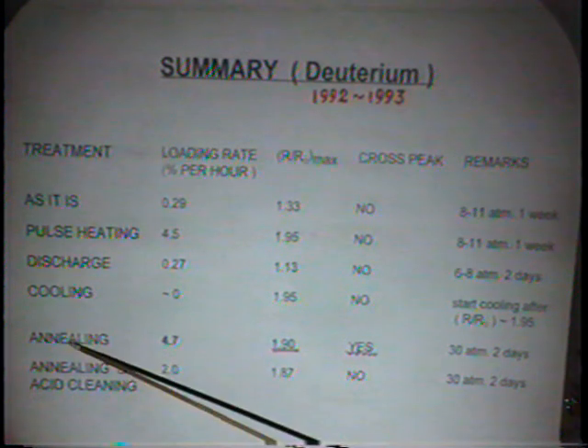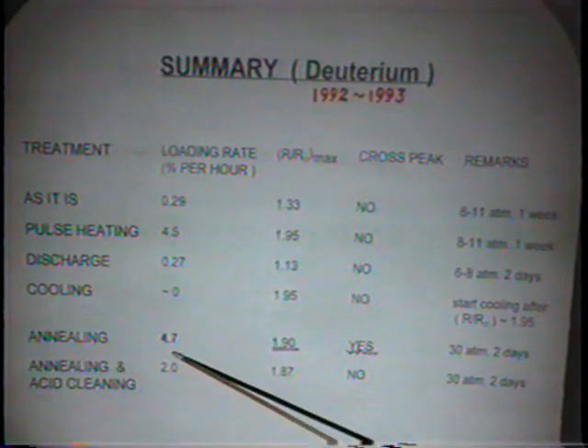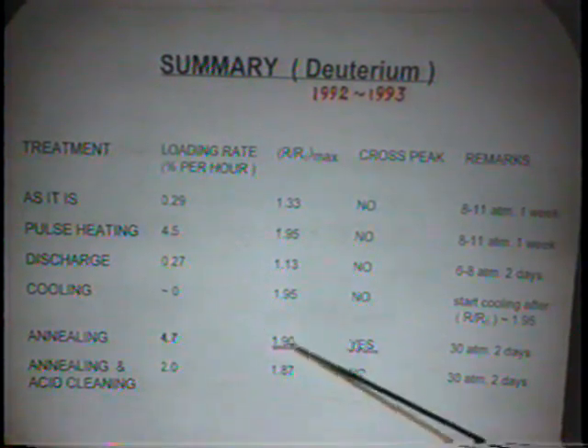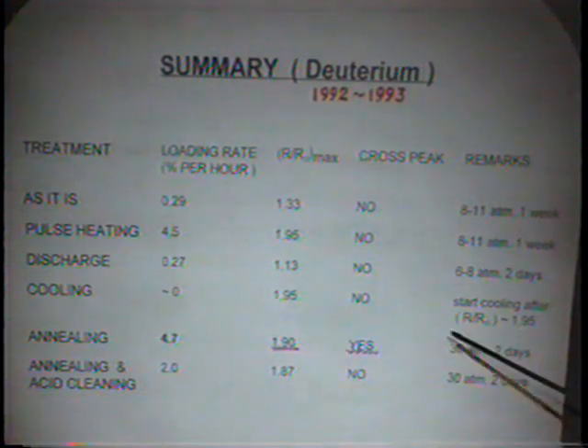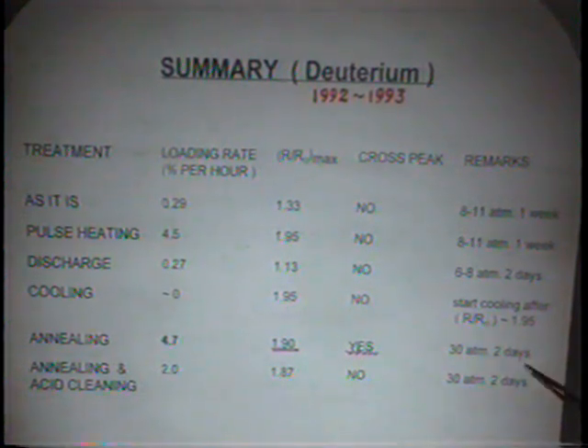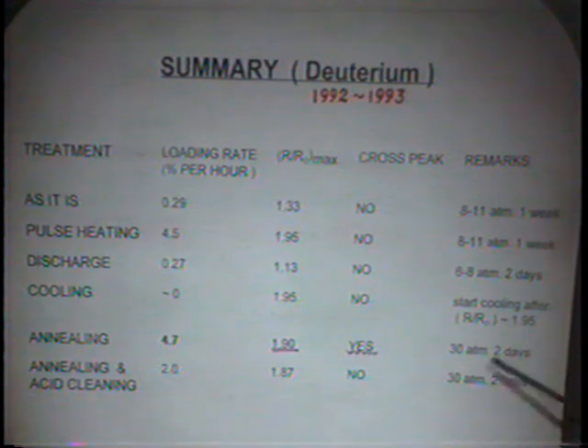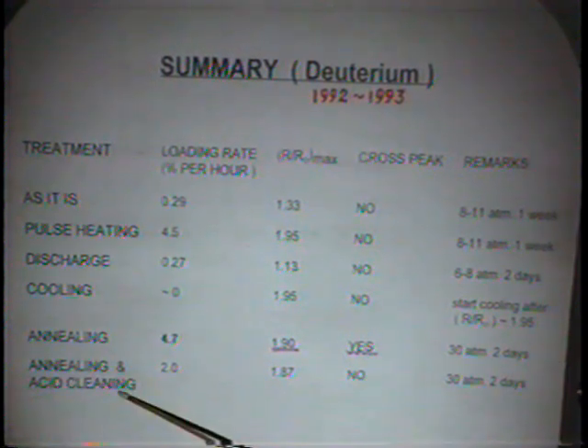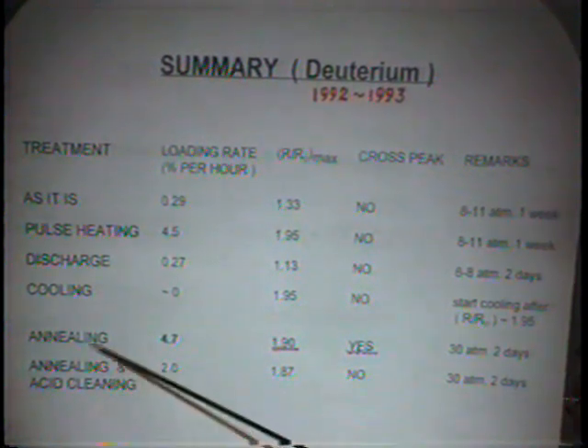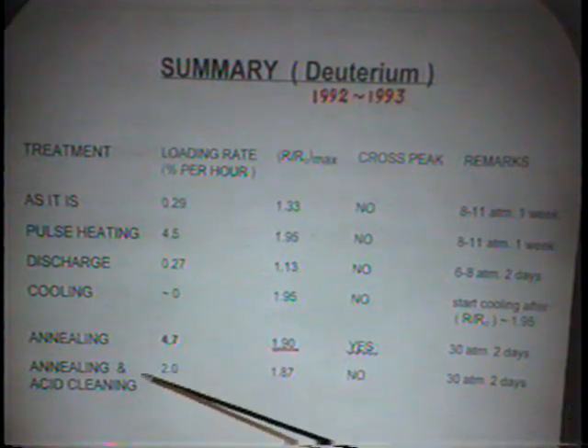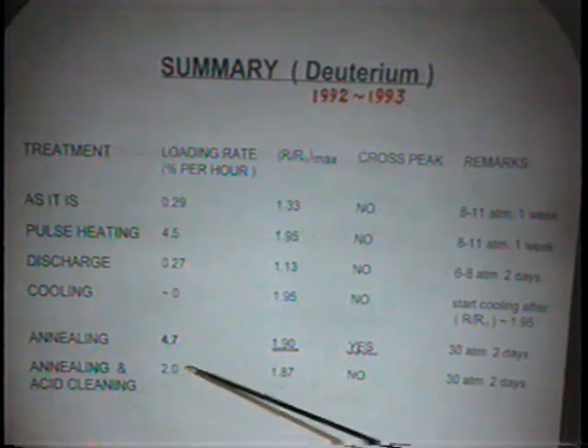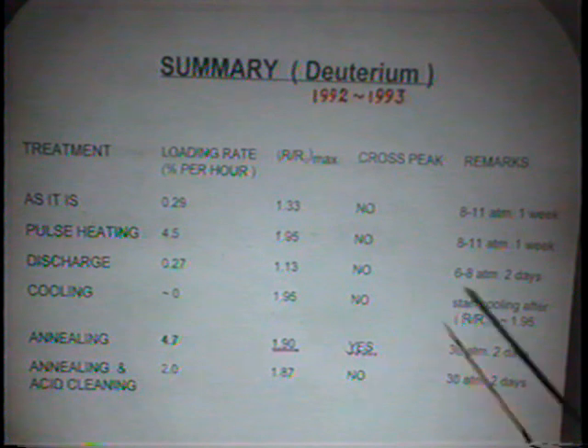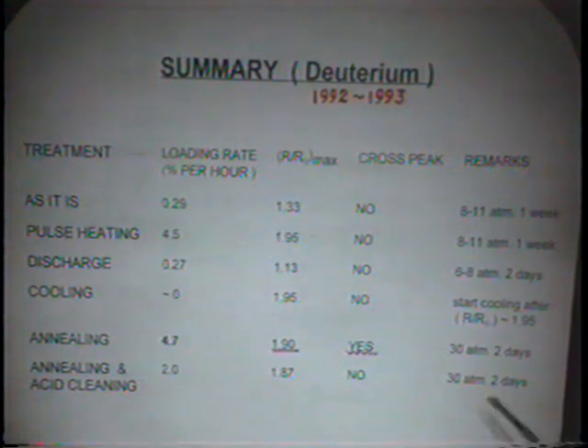If we did the experiment after annealing, the loading rate is quick, the loading ratio is high, and across the peak, 30 atmosphere after 2 days. And we tried to use acid cleaning. Seems it's not very good. After the cleaning, the loading rate is low, and we cannot cross the peak with the same atmosphere in 2 days.